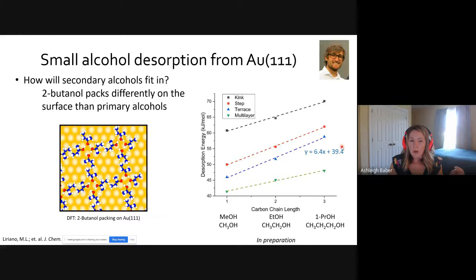One thing that we want to follow up on, again, this is DFT from that same paper, but if you notice looking at 2-butanol, 2-butanol has a different molecular packing on a gold 111 surface. The molecules aren't all aligned. You don't get that interaction between the carbon chains like you would on some of these other primary alcohols. And so how does that affect the desorption temperature of, for example, 1-butanol versus 2-butanol?